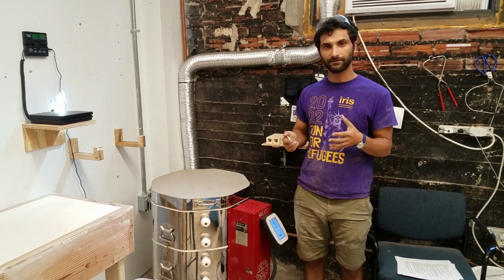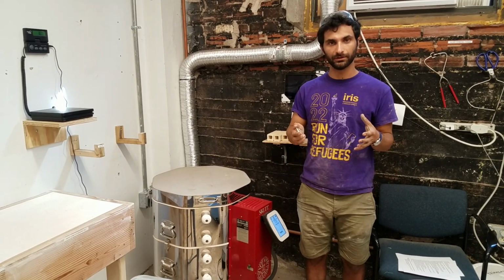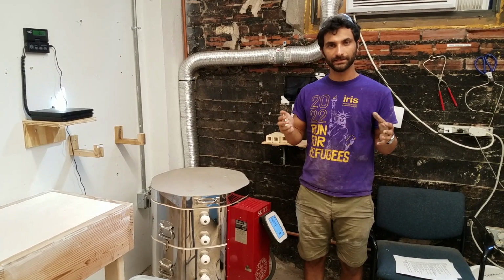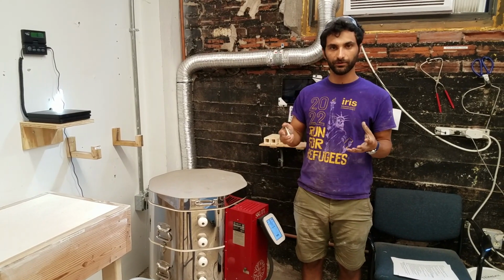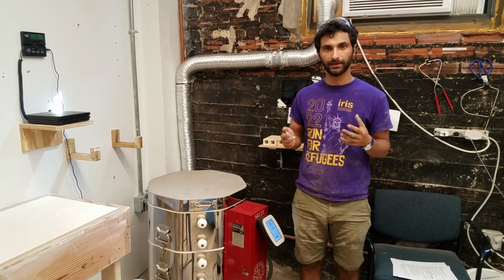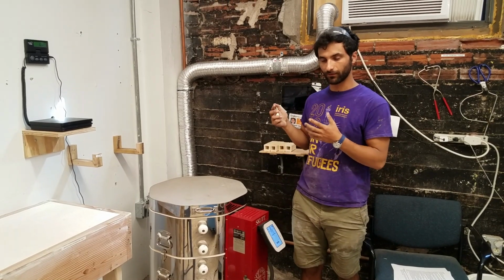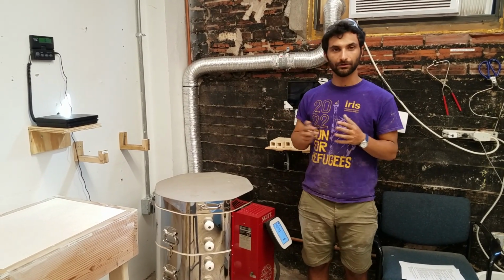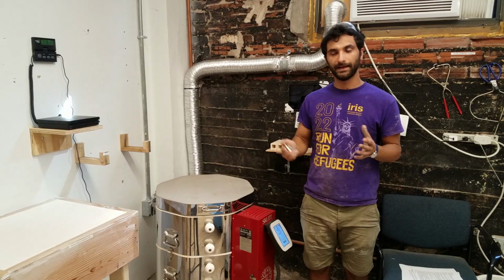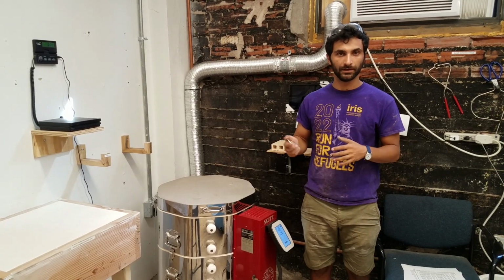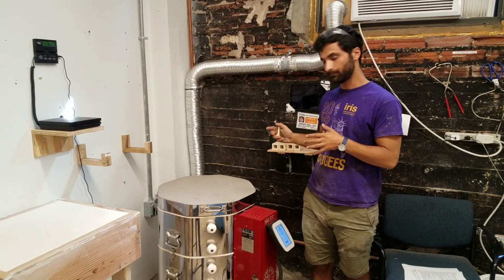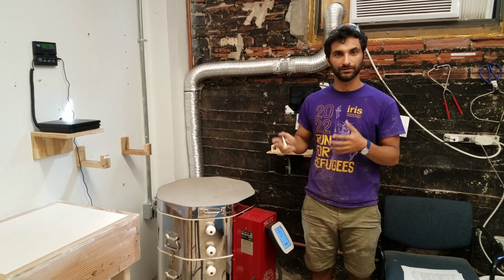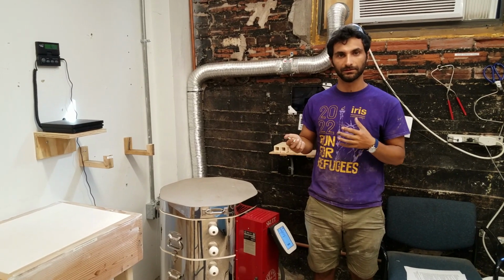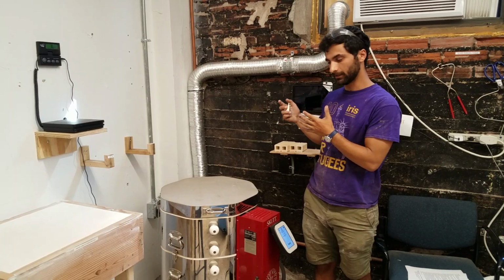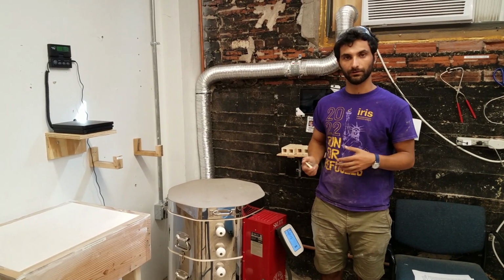So a bisque firing is done at a lower temperature, and the purpose of that is to drive out all the organic material in the clay and get it really super nice and dry and ready for the glaze firing. And that takes a longer amount of time. It's about 12 hours, and then it takes about 12 hours just to cool down. So it's about a whole day of firing, and that uses more electricity, so it's about $10 to run a bisque firing cycle in the kiln.